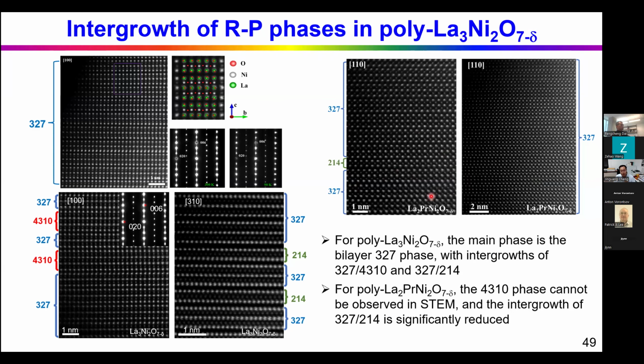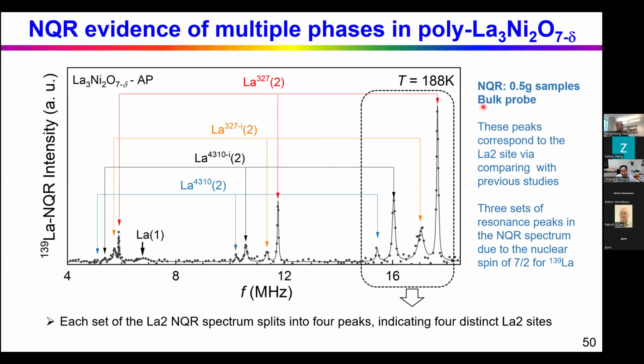But you know the TEM is still a local probe, so we also use the NQR as a bulk probe, because we measured 0.5 gram polycrystalline samples. So this is for the undoped sample. We observed this very complicated structure. So I will skip the details for this. Basically, this is lanthanum NQR. It has a nuclear spin 7/2. So we should have 3 sets of peaks. This is okay. But for each set, we found that the peak actually splits into 4 peaks. This indicates that there are 4 distinct lanthanum 2 sites.